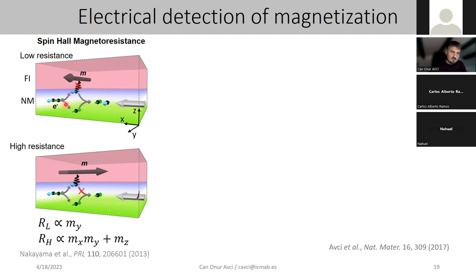and you have a large spin Hall effect in this metal, there is absorption or reflection of the spin current at the interface. If you have a collinear state between the spin accumulation and the magnetization, you have a reflection of the spin current. If you have orthogonal alignment between the spin accumulation at the interface and the magnetization, then you have an absorption. This creates a tiny change in the longitudinal resistivity of the normal metal. So even though the current doesn't go into the magnetic layer, you still get a magnetoresistance behavior. And this magnetoresistance behavior also shows up in the transverse Hall effect measurement.